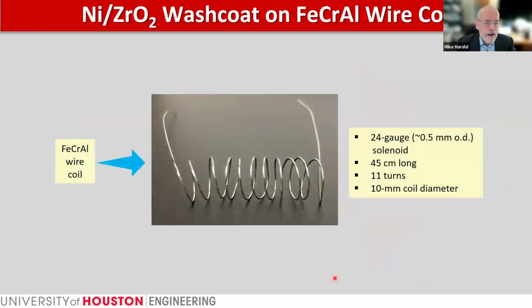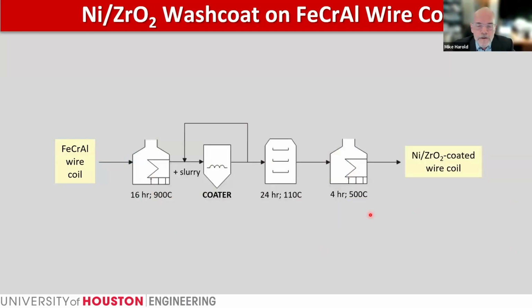coil. This is an iron, chromium, aluminum metal, otherwise known as Kanthal. It's a common material that has the right kind of conductivity range wherein one applies a voltage across the wire and it heats up to a temperature of interest. This is going to be basically the reactor in the experiments we're doing, about 0.5 millimeter in diameter. This particular wire is about 45 centimeters long with 11 turns. For those electrical engineering interested folks in the audience, this is a solenoid, basically. One can produce a magnetic field by putting current through this coiled wire. I'll get back to that a little bit later.